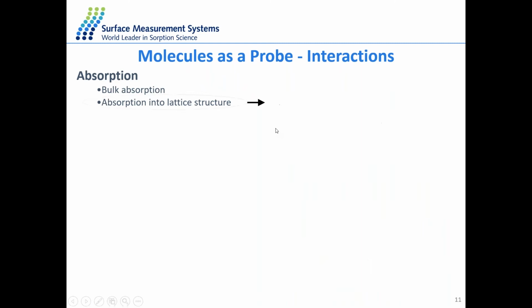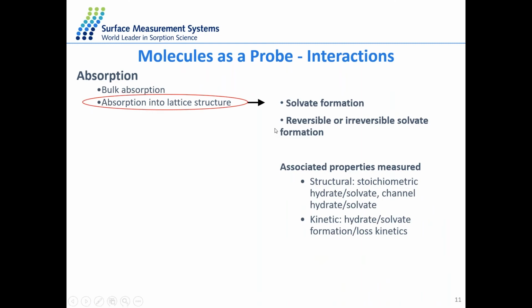The last kind of interaction is absorption into the lattice structure, which means the material will change its structure in the presence of any kind of vapor, like water vapor or organic solvent. And this will lead to the formation of a hydrate or solvate. So from the DVS data, we can study the structure of this hydrate as well as the kinetics information about its hydrate formation or dehydration. So we can get all those kinds of interactions from different probe molecule and solid interactions, and from the DVS experiment, we can calculate those properties.